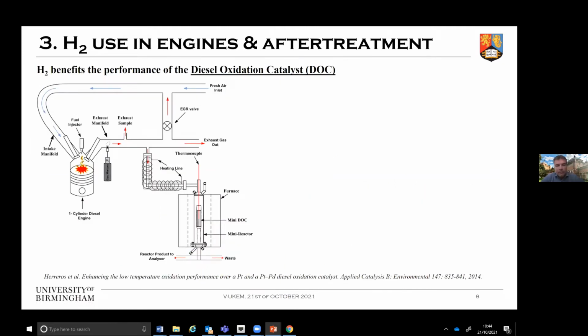And then going a bit more in depth on the case study that we have been investigating. The first one, I have prepared a schematic here, and we will have in this case a diesel engine, and then we are trying to investigate the effect of hydrogen being injected upstream of, in this case, a diesel oxidation catalyst. We have done the test with a small catalyst inside a reactor, inside a furnace, because this allows us to study independently residence time through the catalyst, temperature of the catalyst, and species concentration after the catalyst, independently of the engine operation.